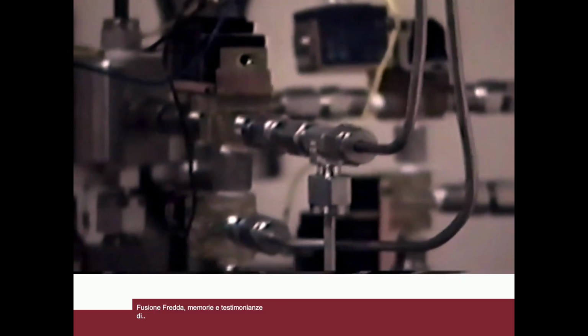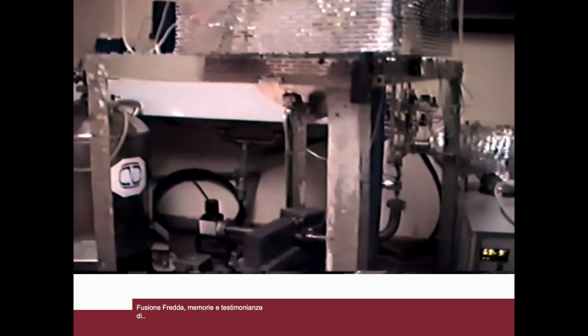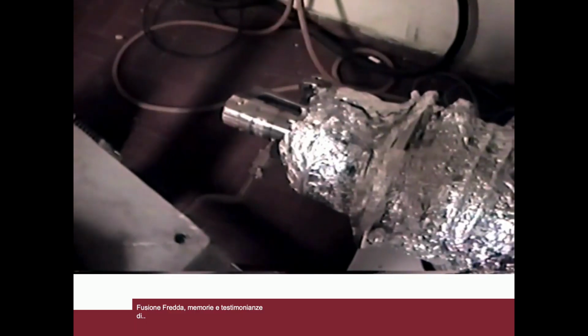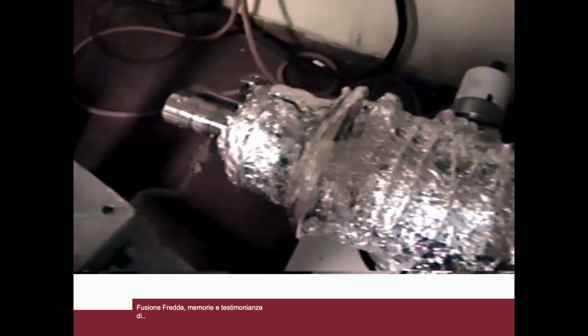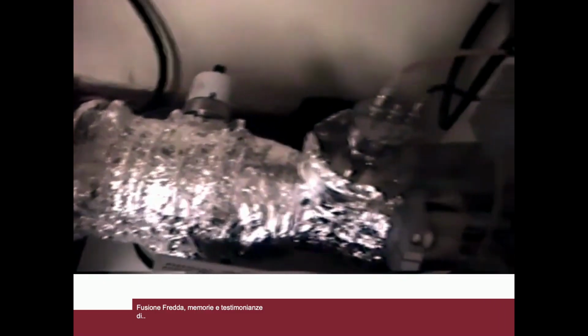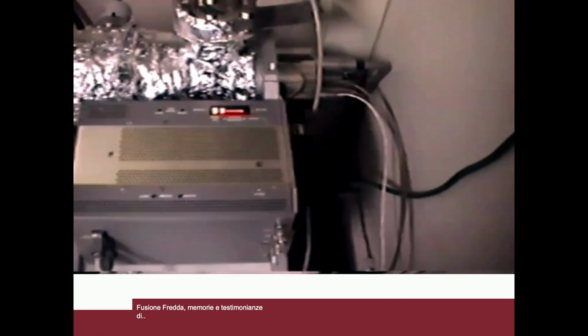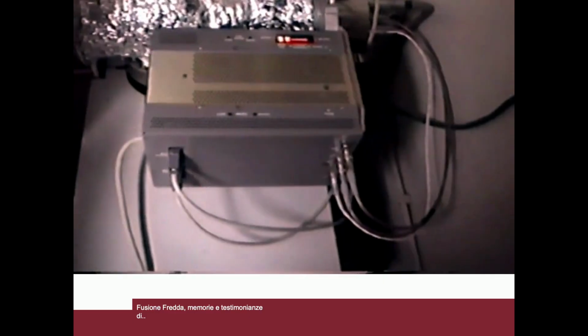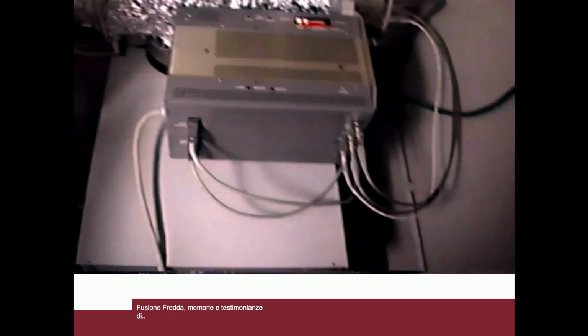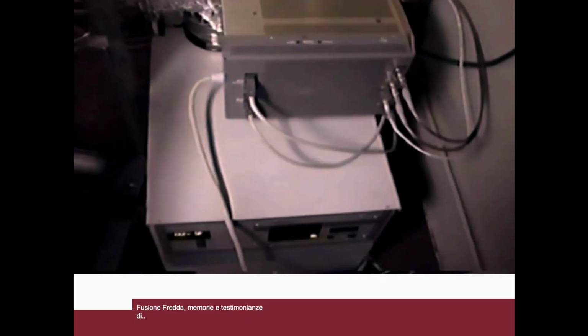Upon command, the inlet needle valve into the spectrometer opens. The spectrometer chamber always works at a pressure of around 10 to minus 9 millibar. The pressure gauge inside the chamber controls the closure of a needle valve if the pressure rises above a preset value. It can be observed that all the connections are made with Swagelok pipes.